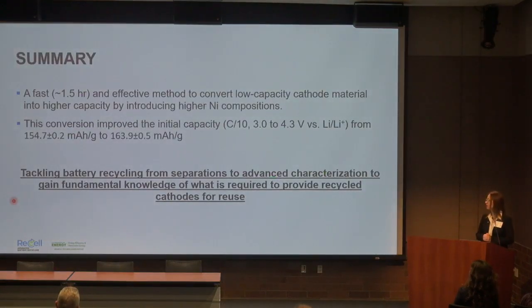So I just wanted to highlight this project. We were able to deliver these fast, effective methodologies for converting low nickel composition cathodes to higher nickel composition cathodes, but we still have a long way to go. And the feedstock is continuously changing. So across ReCell, from every step of the direct recycling process, we have many different researchers working on different paths. And that's really important so that we can handle these different feedstocks. And I wanted to highlight the imaging method because we are tackling battery recycling not only from a separation standpoint, but from an advanced characterization standpoint, so we can gain the fundamental knowledge that is required to provide these recycled cathodes for reuse.